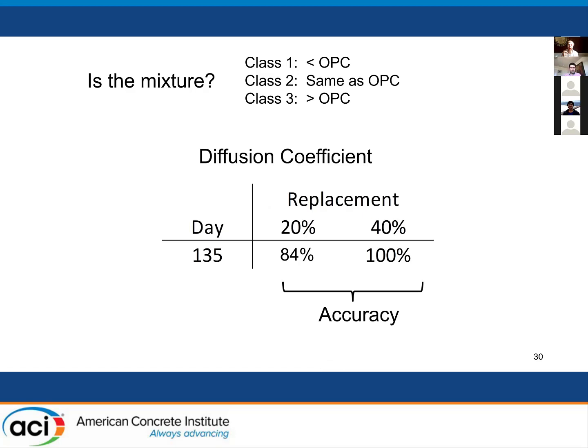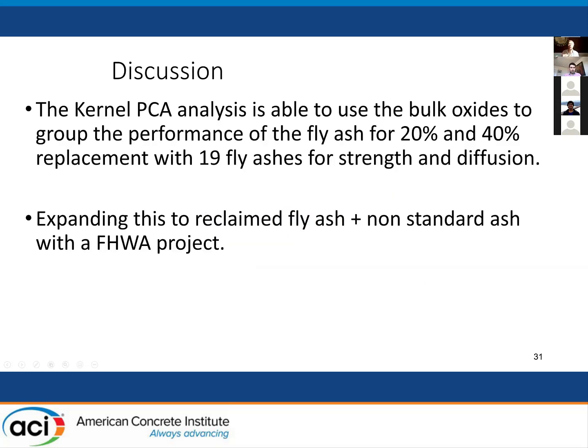Pretty neat, huh? We can actually predict diffusion coefficient as well. Diffusion coefficient, you know, the one that actually predicts the rate at which ions are going to penetrate inside of our concrete, right? And with 20% replacement, we're at 84% accuracy, and 40% replacement, we're at 100% accuracy. That's pretty awesome, right? So the Kernel PCA analysis is able to use the bulk oxides to group the performance for fly ash at 20% and 40% replacement level for these 19 raw ashes that I showed you today.